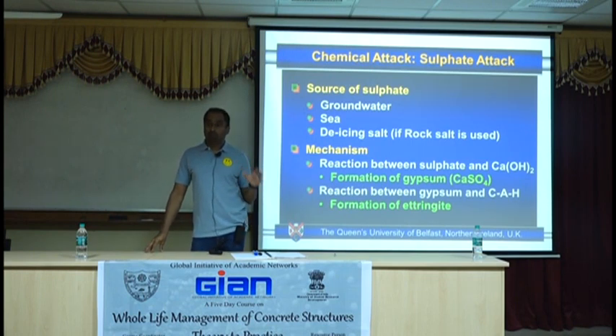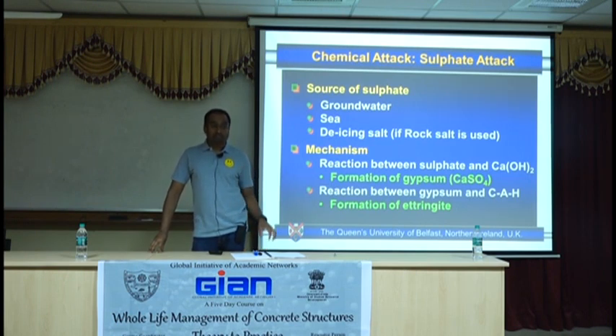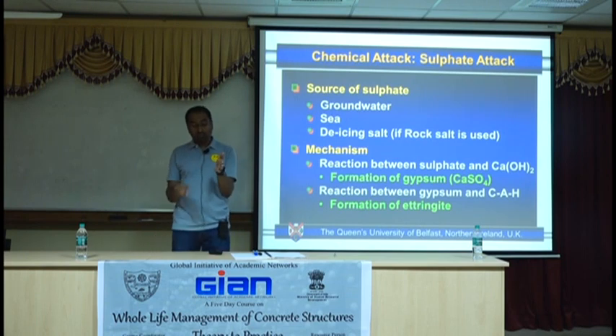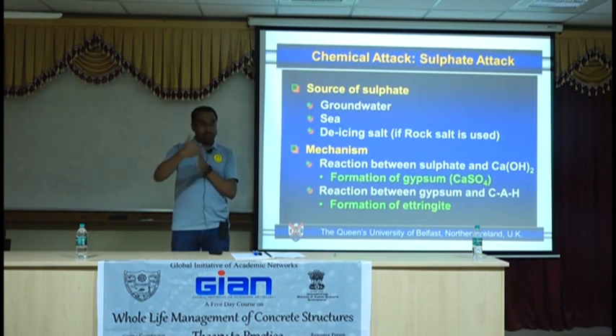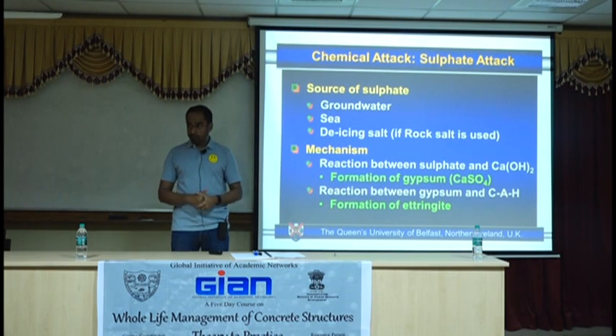If you put sodium sulfate or sulfuric acid — H₂SO₄ — it can combine and attack the calcium hydroxide to form gypsum. It'll powder the cement away, and the concrete away as well, because you will see it in the form of acid attack. If sulfuric acid is attacking the surface, you will slowly start to see that the cement recedes, the aggregate will start to pop out, and eventually the aggregate will fall out.